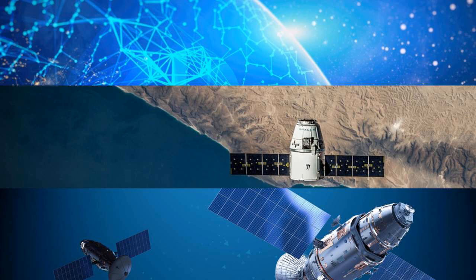So traditional white paints or multi-layer insulation materials are not necessarily sufficient to provide the exact absorptivity-emissivity balance. And the orbiter's infrared hyperspectral spectrometer, in particular, requires stable temperatures and stray light suppression during these longer duration observations. So Nano Black was selected because it provided precisely that alpha-epsilon balance, absorbing solar energy efficiently while radiating it away at a controlled rate. It prevented freezing in lunar night and mitigated overheating in lunar day. So it's thin, lightweight, reduces mass, which is critical for both landers and orbiters.